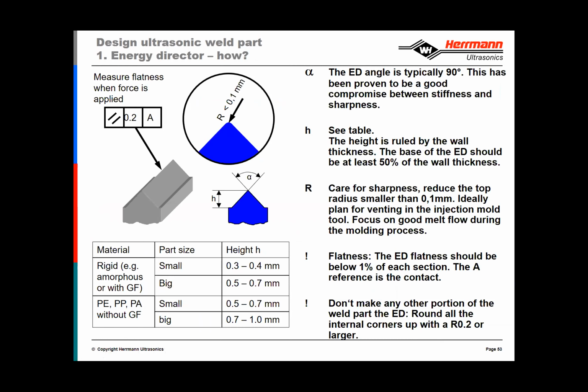criteria that has to be followed is the flatness of the parts. So what we're talking about is across this surface. So make sure that there's not any warp or sinkage or sink marks, anything like that across there, because if we don't get even contact of the height of the energy director against the opposing parts, there could be weak welds or in some cases even leaks in those places.